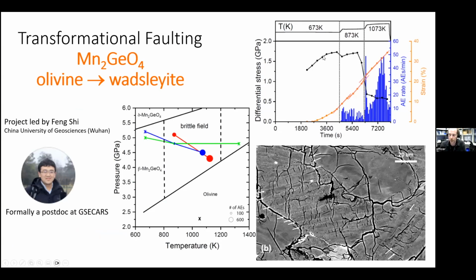You get another plot that looks like this. And then you can see these little dots here are the high pressure phase dotting. So these are where you can have slip within these bands. Basically, olivine to Wadsleyite in this material behaves identically to olivine to ringwoodite in Mg2GeO4.